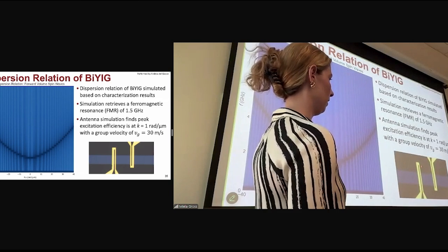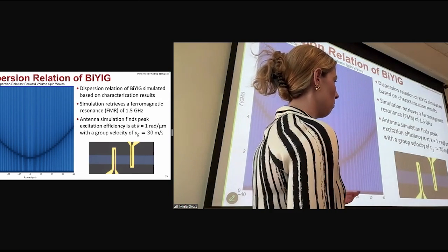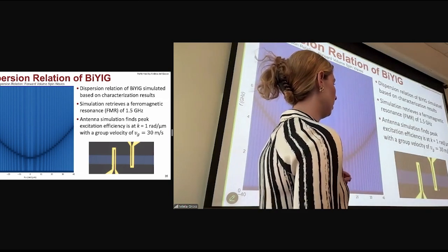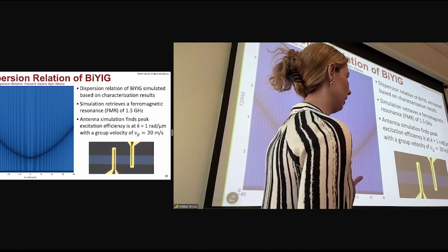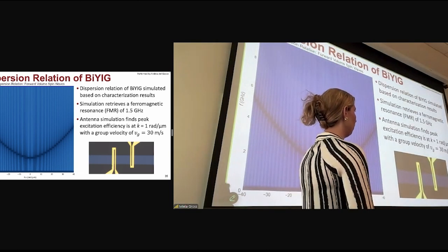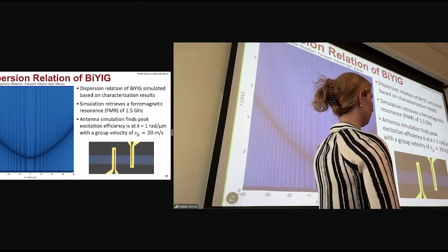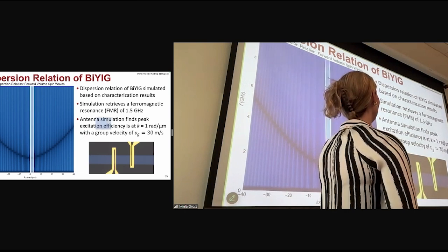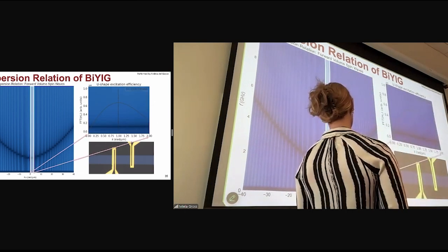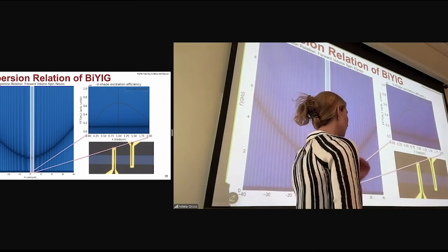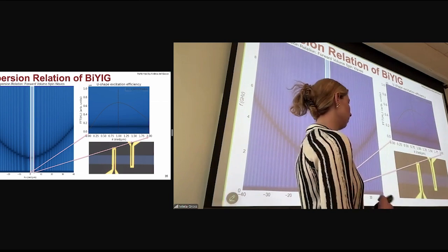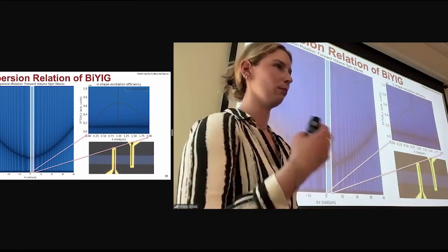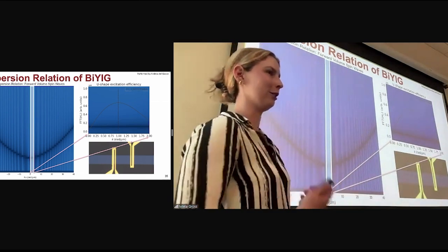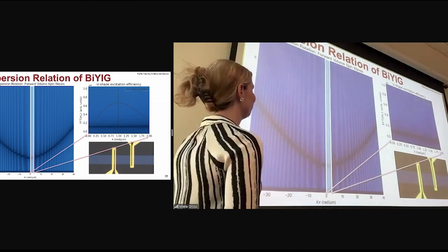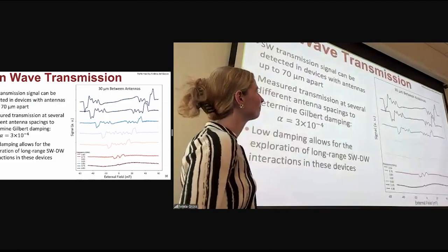What we found is that these antennas most efficiently excite low mode spin waves of a k around 1 radian per micron, which have a group velocity of 30 meters per second. And that's what this simulation looks like. So we have some low mode spin waves. However, we want to see more progressive domain wall motion. So it's actually advantageous for our purposes here.